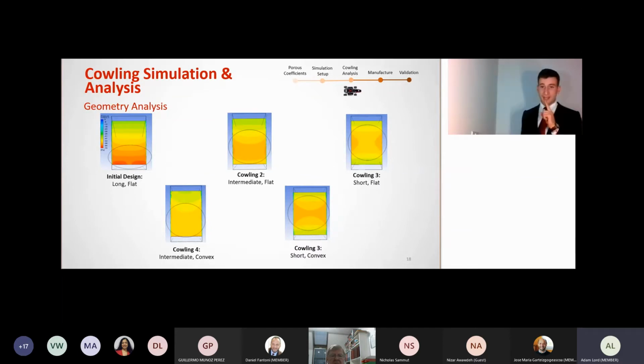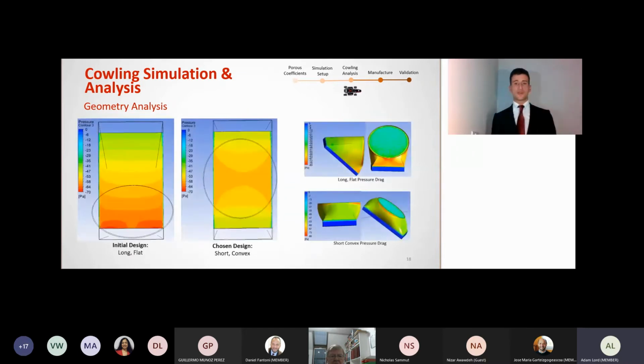In fact, the largest pressure drop is concentrated on a localized area towards the bottom portion of the radiator, and then by shortening the shroud geometry and by introducing a more convex shape, flow distribution was actually improved. The drag over the cowlings was also examined and was found to have negligible effects on performance. So in the end, the short convex shroud was chosen for manufacture, firstly being the lightest design, but most importantly, after showing the most ideal flow distribution in simulation.